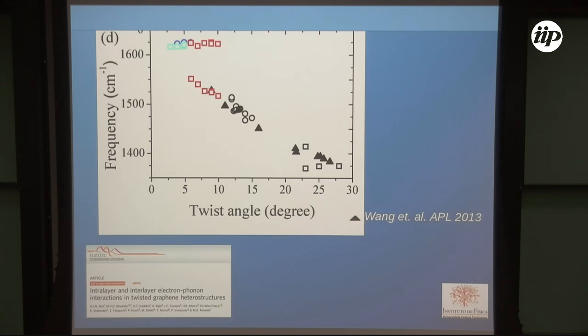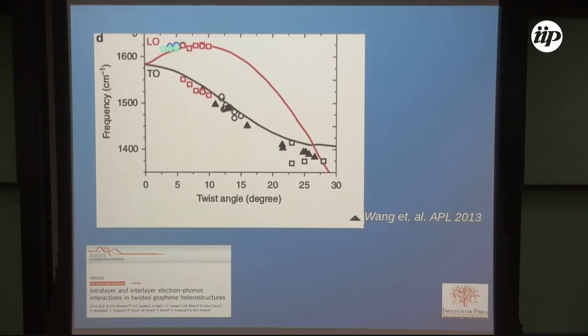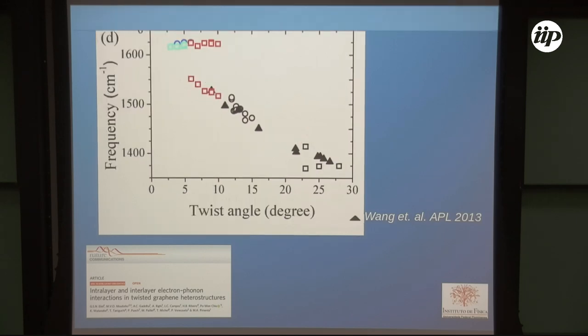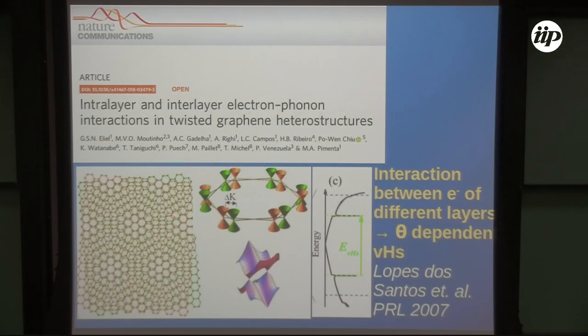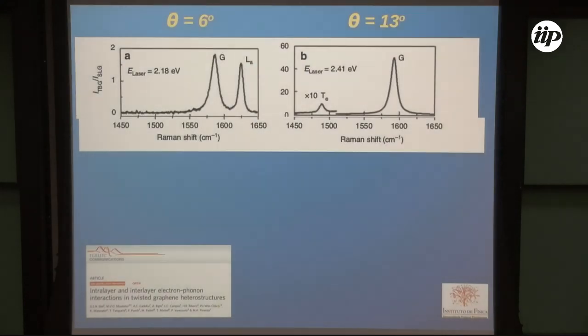So if we take different angle unit cells, now we see how the two phonons that we call LO and TO, the two phonons that are degenerate in the zero degree case, now they will come from a place that in monolayer graphene was not at the gamma point. So I fold these points, not at the gamma point, to the gamma point, and this I can do as a function of angle. When I do the calculations, a very simple calculation, you just take your phonon frequency and you fold them. Also, I forgot to tell that the theoretical modeling was done by myself, but now with the very special help from Marcos Moutinho. So he did that.